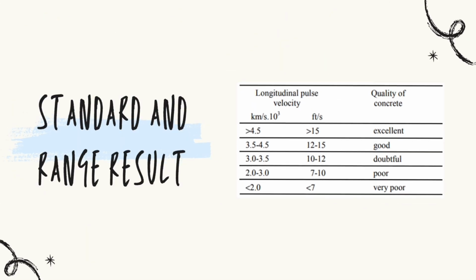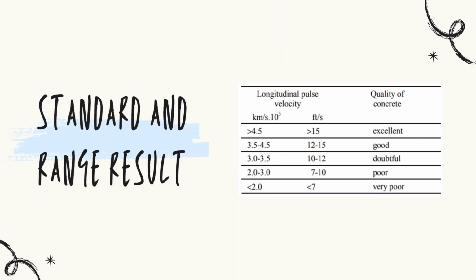The standard and range of result of UPV. In standard and range of result, we measure based on pulse velocity. If more than 15 is excellent. If 12 to 15 is good. If 10 to 12 is doubtful. If 7 to 10 is poor and below 7 is very poor.